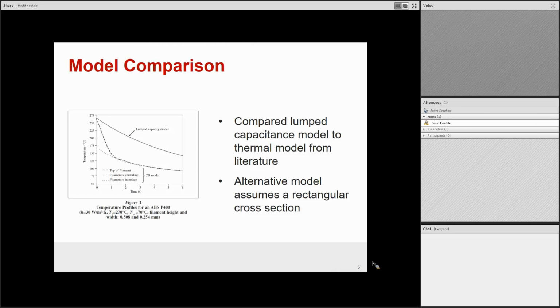Do the 2D models make the same assumptions as the lumped capacitance model? Like you had some assumptions listed in the previous slide, the constant temperature. Does the 2D model have the same assumptions as that? No, the 2D model is mostly based off of solving the entire differential equation. While the top model, the lumped capacitance model, is per unit cross section, the temperature is completely the same. In the 2D model, the cross section temperature is different. That's why it gives the different lines of top filament, filament center line, and the filament interface with the build plate, because of the different cross sectional assumption.